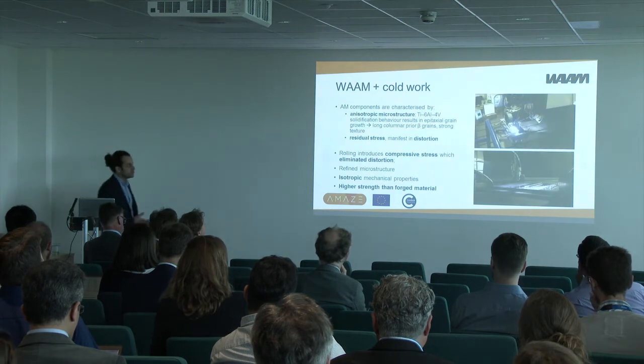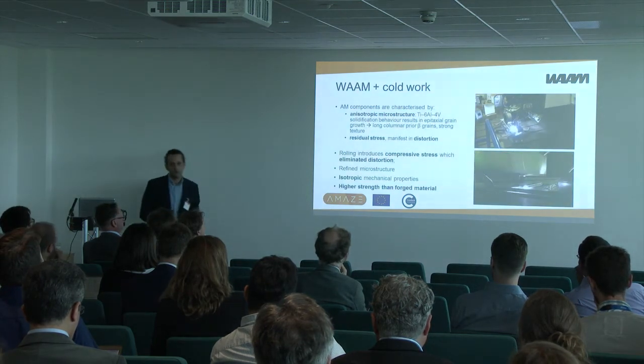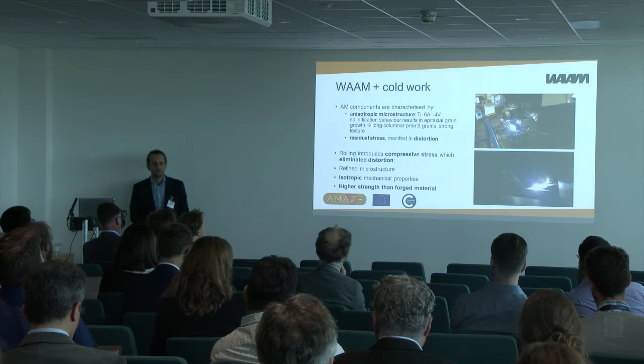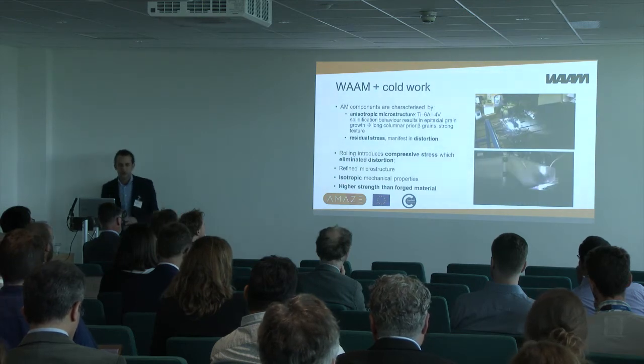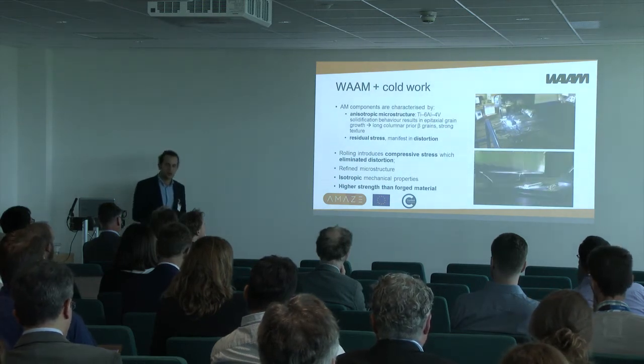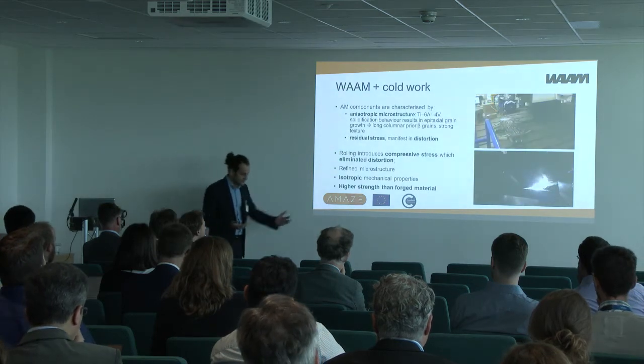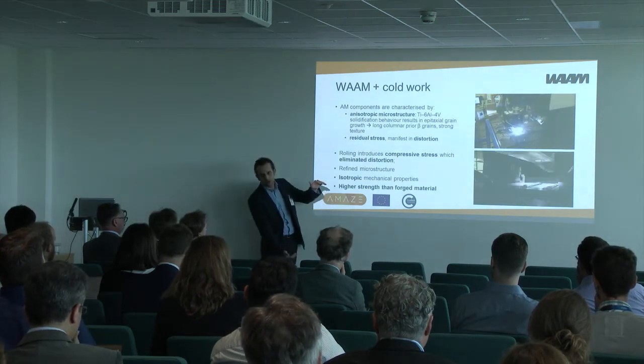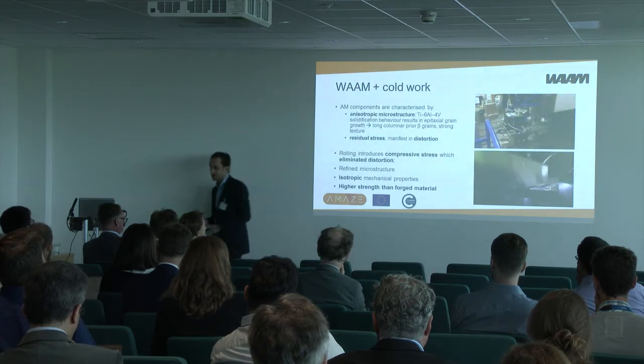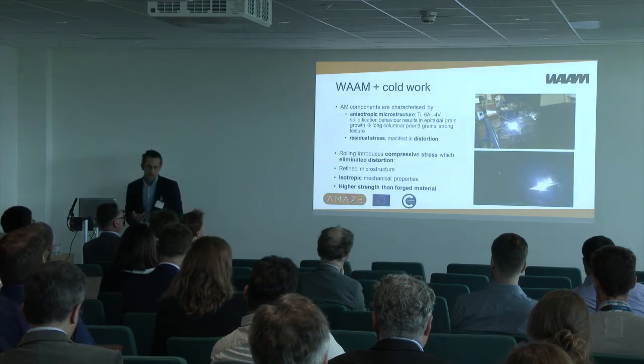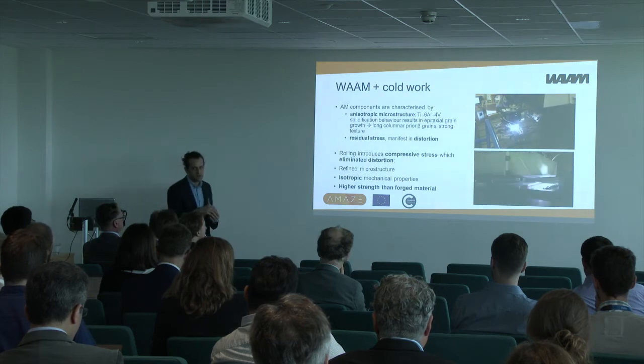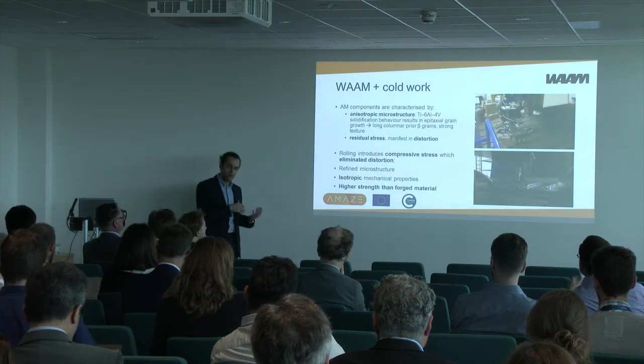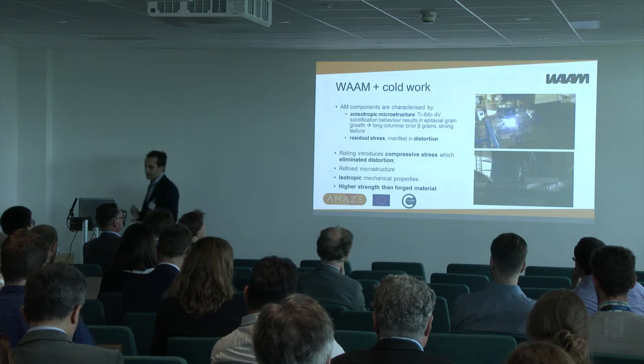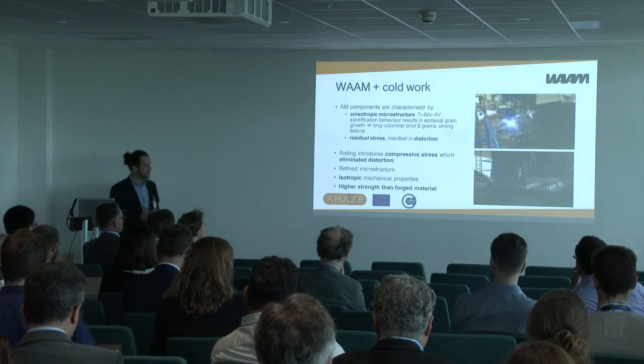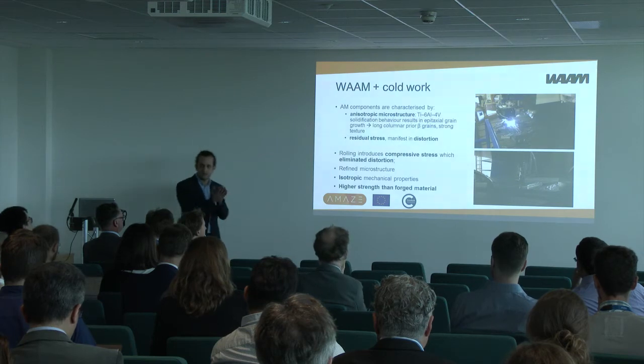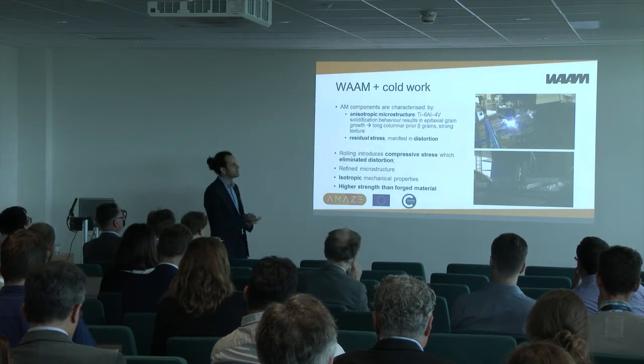So why do we have to do cold work? What's the requirement for cold work? Well, if you're familiar with the microstructures developed by Ti64, for example, in this process, we know that the grains are very anisotropic. We've got components that are this big, and you can see the grains going all the way from the bottom to the top. This results in mechanical properties that are also anisotropic. Typically, in the vertical direction, the elongation is very good, but the strength is low, and vice versa in the horizontal. And then there is, of course, the problem of residual stress and distortion, which can be tackled by the symmetrical strategy, but sometimes that's not a possibility.